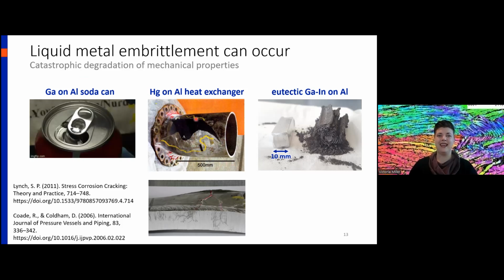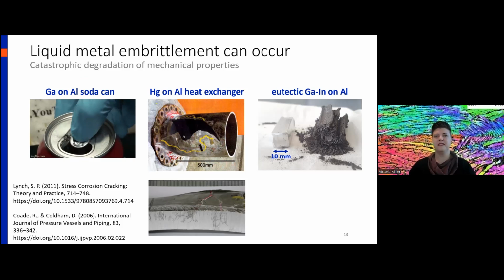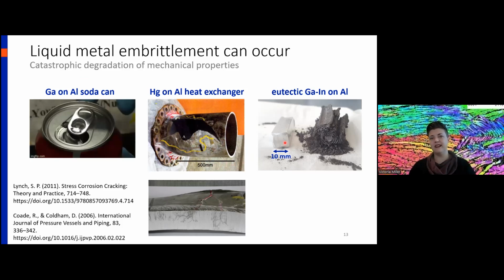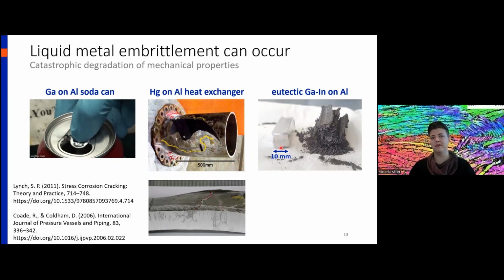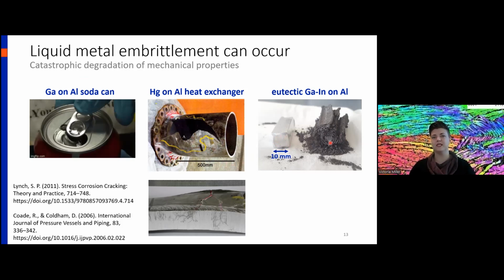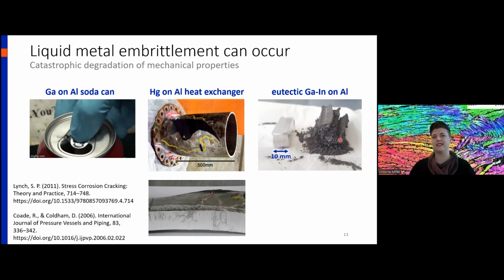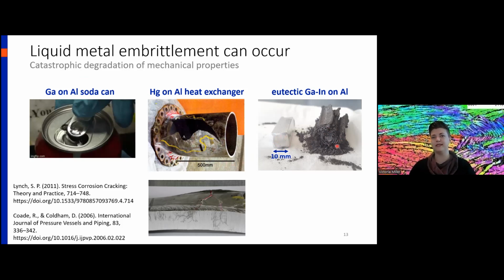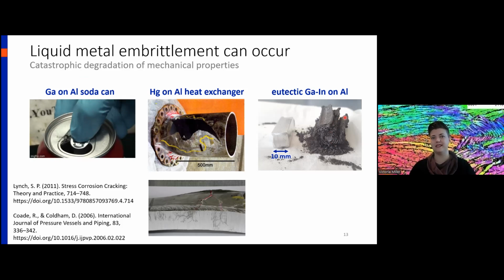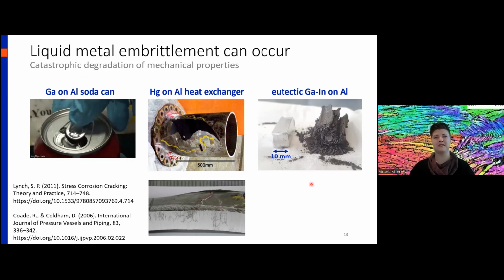And you can see catastrophic failure. And this over here is a piece of bulk aluminum where this half was exposed to a eutectic gallium indium mixture. And you can see that it just sort of disintegrated into this pile of gray dust.